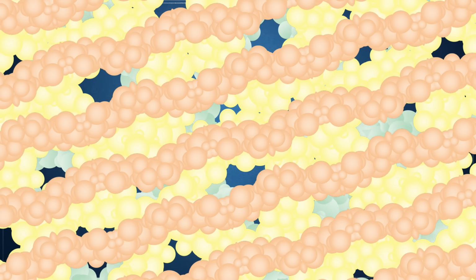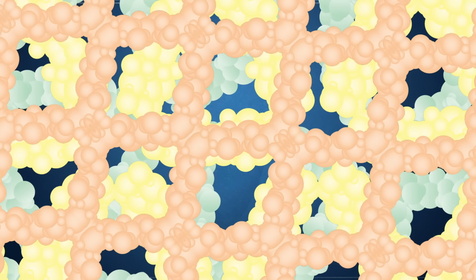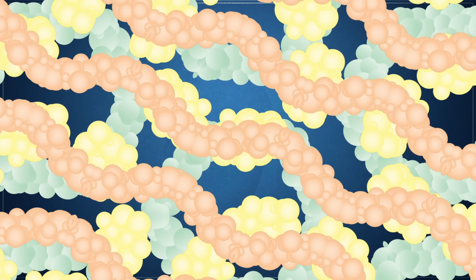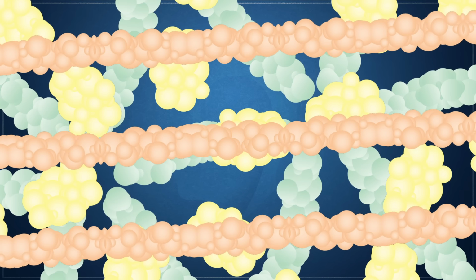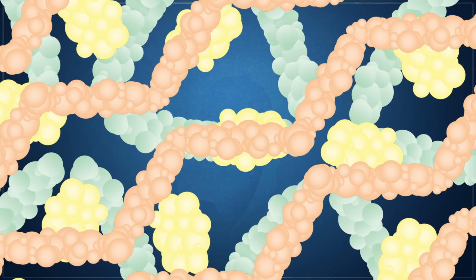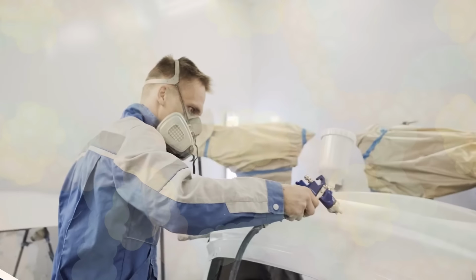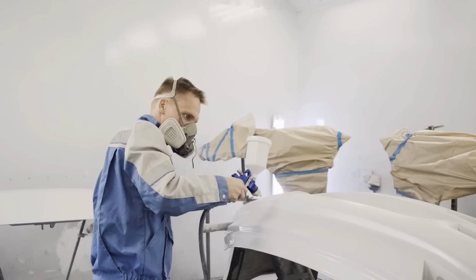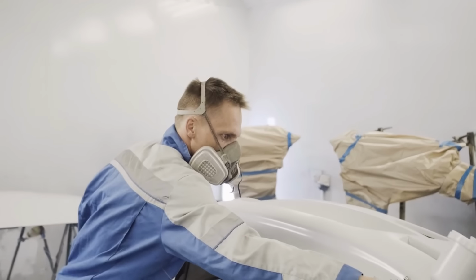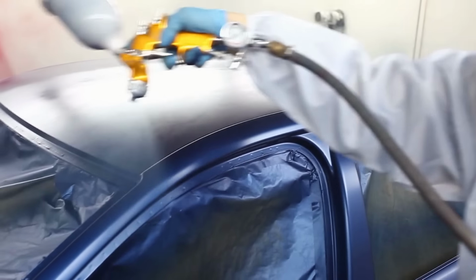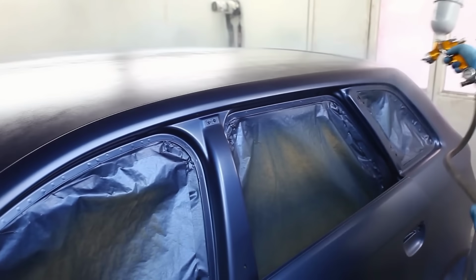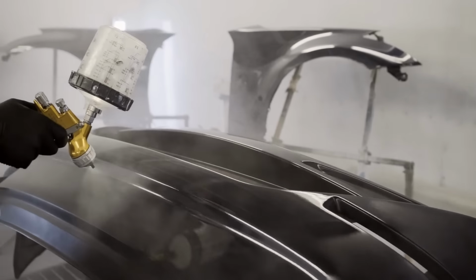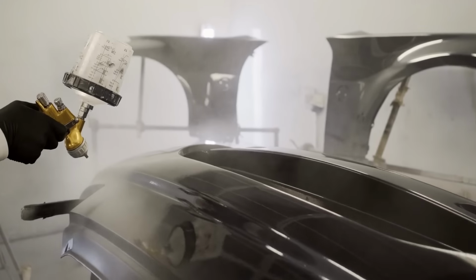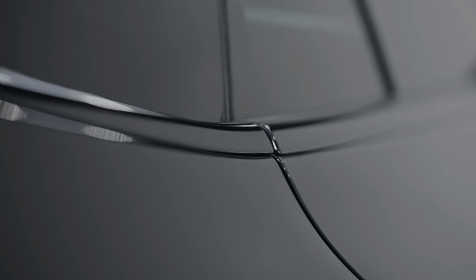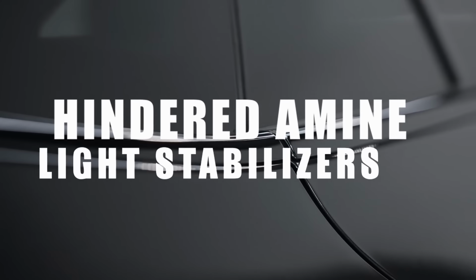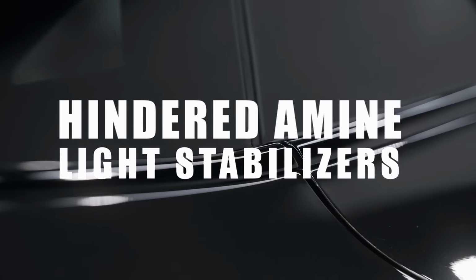By adjusting the constituent resins and their quantities, as well as the catalyst formulation, the sequence and rate of how this polymer network is formed can be modified, and the properties of the composite film adjusted to suit the needs of the product. Primers, for example, are formulated to produce a larger proportion of polyester resin in order to create a higher building film, while base coats are designed to form a high pigment retention film. Clear coats, on the other hand, are engineered to be tough and chemically resistant while providing UV resistance through the inclusion of ultraviolet light absorbing additives and chemicals known as hindered amine light stabilizers, or HALs.